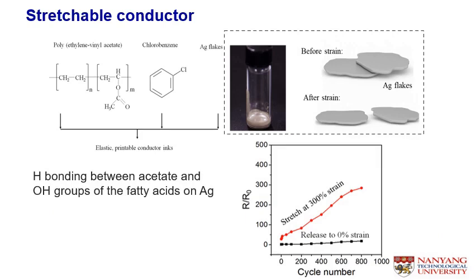And the stretchable conductor is realized in the presence of an elastic printable conductor ink that comprises of metallic silver flakes. When we use just the metallic silver flakes, the stretchability can be sustained at 300% strain. However, the resistance will increase incrementally as a function of a cycling number. Therefore, the cycling stability of the conductor needs to be improved.